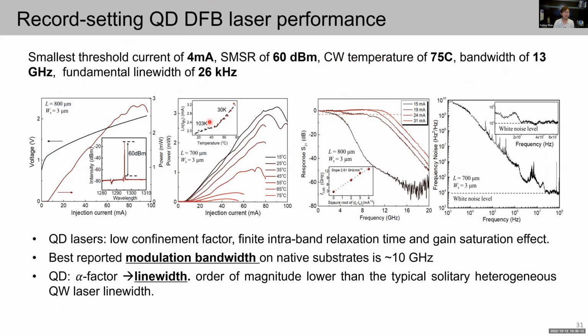So here the laser shows a threshold current of 4 milliamp, a side-mode suppression ratio of 60 dB, continuous-wave operation up to 75 degrees C, a 3 dB bandwidth of 13 gigahertz, and a fundamental linewidth of 26 kilohertz. So what I want to emphasize is the last 2 points.